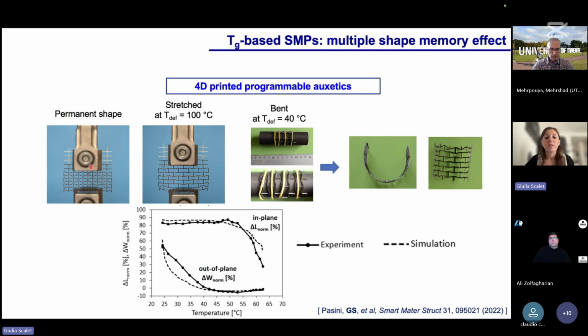And so we play with this material. We coupled it also with some architecture, such as this auxetics. So we were able to achieve different sequential out of plane and in plane shape changes using this resin, and this allows us to achieve programmable shape changes based on our need. We also verified through numerical simulation, in this case with a simple rheological model, the classical generalized Maxwell one, in order to support this design step.